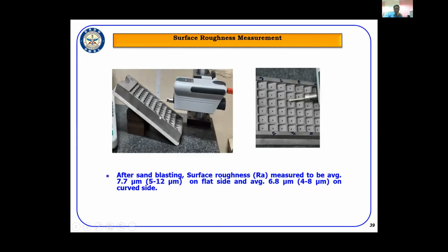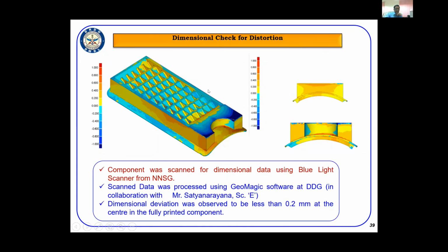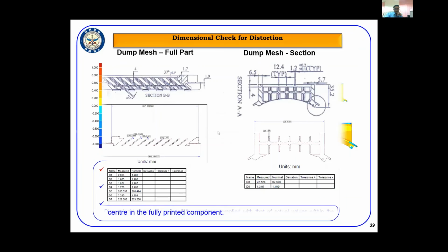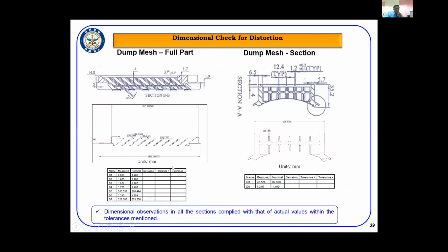So then after sandblasting, again we have gone ahead to understand the surface finish at each and every channel of this component, and on average we could get 6.8 microns on the curved side because of the stepped region. And the component also has been further scanned for the dimensional data using the blue light scanner, and the observation was found to be less than 0.2, which meets the requirements of the designer. Dimensional observations in all sections compared with the actual values are within the tolerances mentioned.